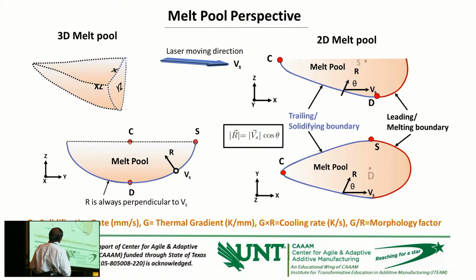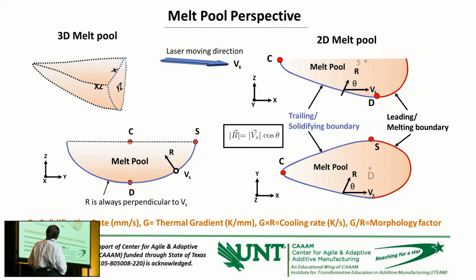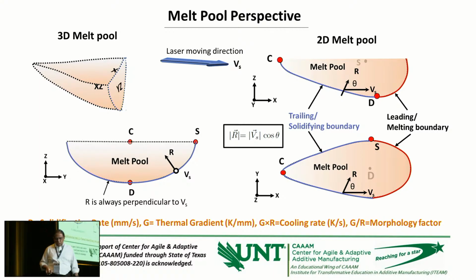The grain growth direction is connected. Theta is the angle between these two parameters, the solidification rate direction and the scanning speed direction. They are related this way. So the grain will grow in that direction, depending upon how fast the beam is moving and how fast the solidification rate is. So they will control how the grains grow within the melt pool, whether they grow straight up, at an angle, or horizontally. Everything depends on the values of these, and these are connected through the earlier equations.